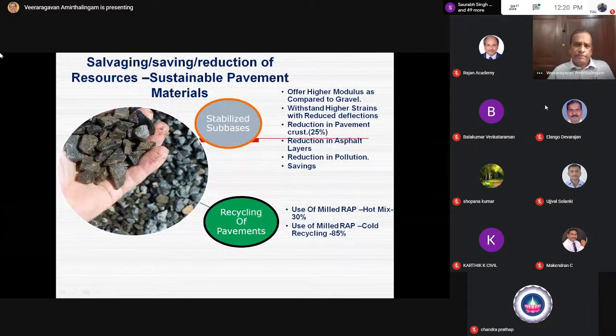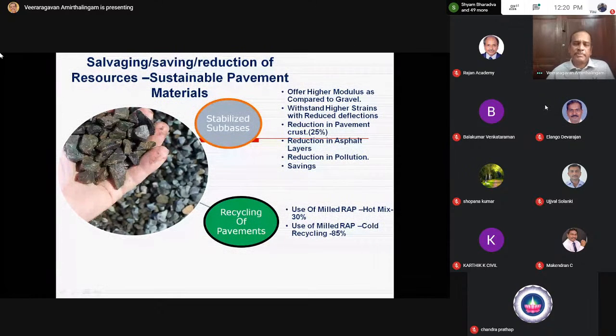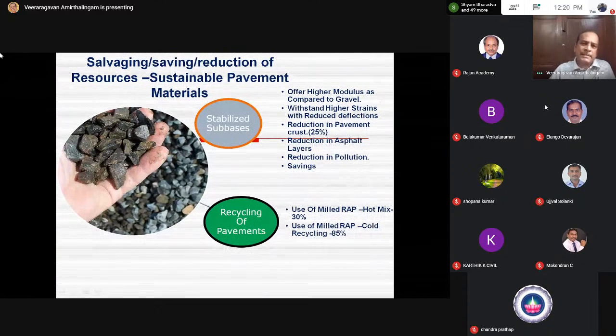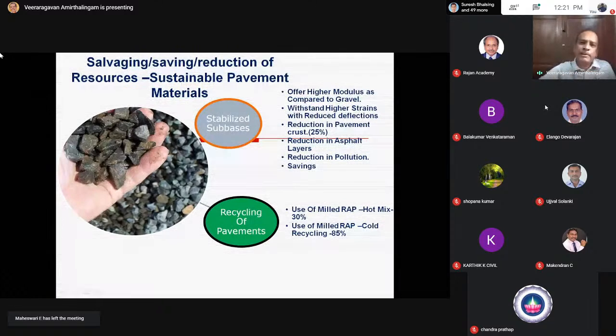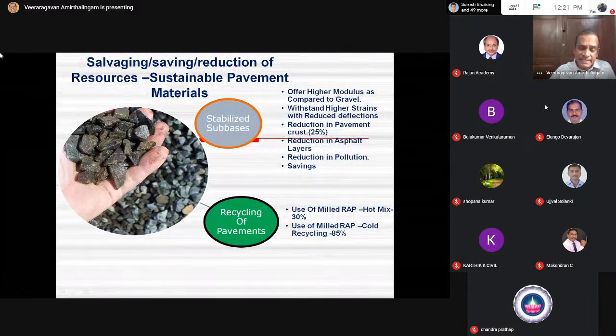Even in the case of rural roads that are awfully bad, again, you can do a full depth reclamation. I can mill the old water bound macadam layers, a part of the old premix carpet layers. Entire metal can be milled. I can add cement and then stabilize that layer. So I am salvaging already constructed pavement materials. I am improving the strength. As a result, I am making use of 100% of the material that is already buried. I am providing only a thin bituminous layer at the top. Will the pavement perform? Yes, definitely. So salvaging, saving the virgin aggregate, reducing virgin aggregate consumption will be the mantra in the years to come for sustainability.